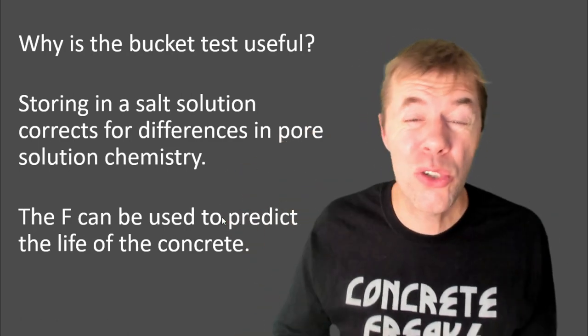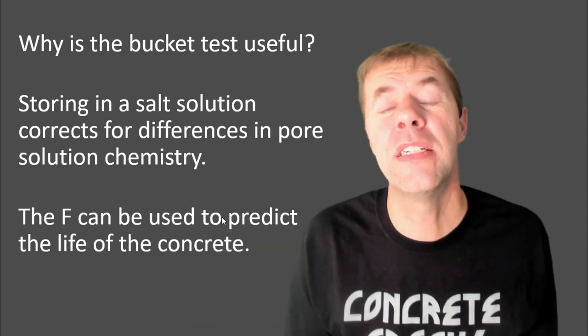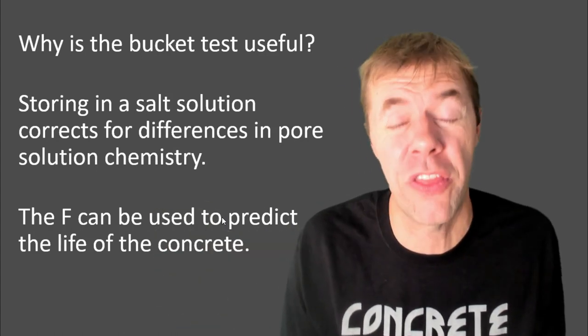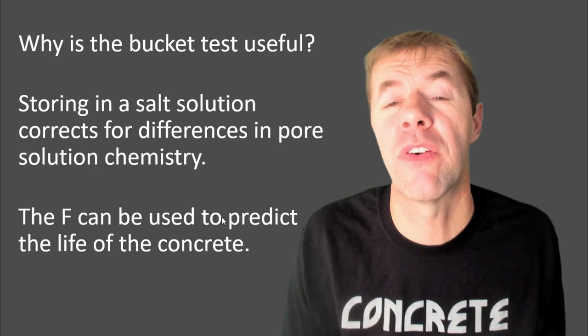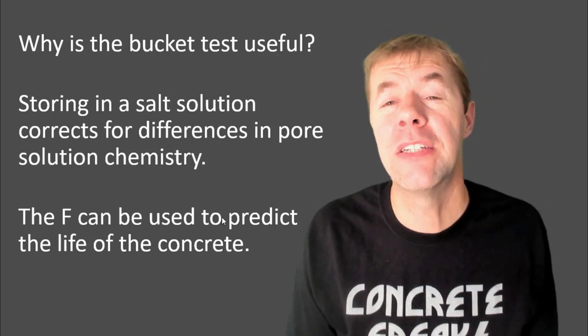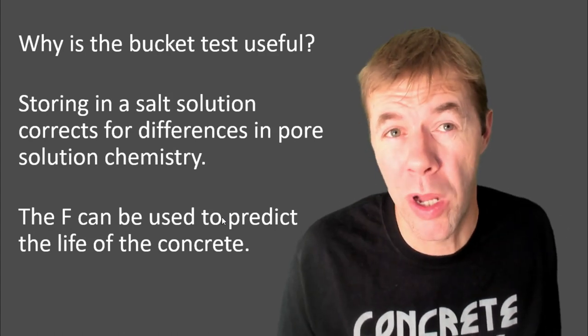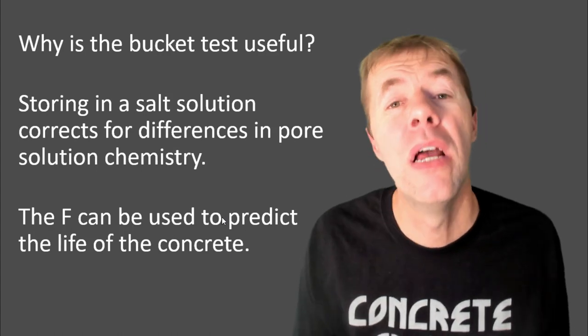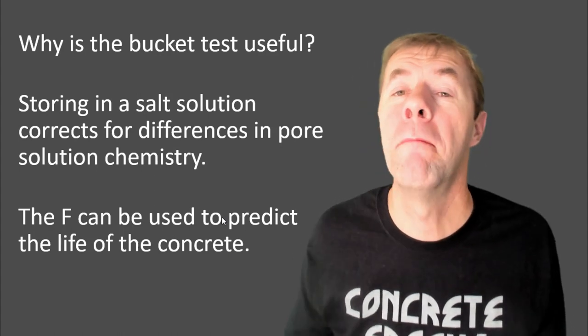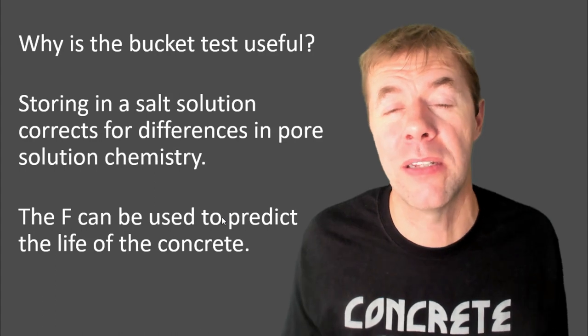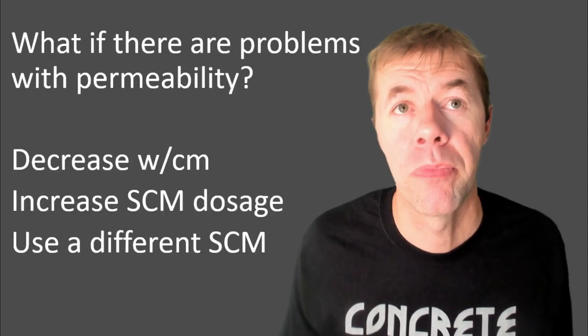Well, storing it in the salts corrects for all kinds of different things, different weird chemistry things that happen when you use different SCMs in your concrete. The F is a much more direct measure as well to predict the life of the concrete. We're not quite there yet, but we're moving towards the F and the bucket test every single day.